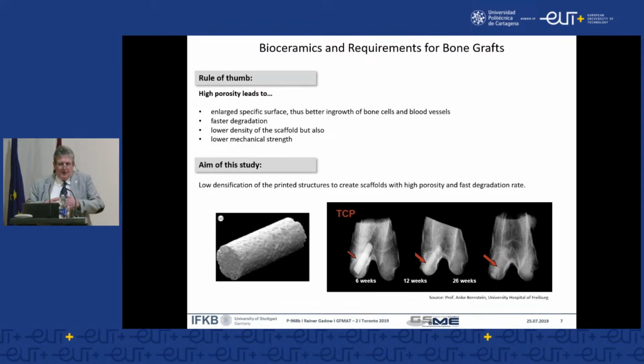And in a second step, and on a longer time range, not only the bone cells, even the blood vessels. That means the complete metabolism of a human being is used and applied to restore the original defect in the skeleton structure. And therefore we have to select materials that have a relatively fast degradation and a low density, and at the very beginning the mechanical strength must not be so high, because the patient in the early phase after the operation is stabilized by other means. The important thing is what happens with the implant after a few weeks.